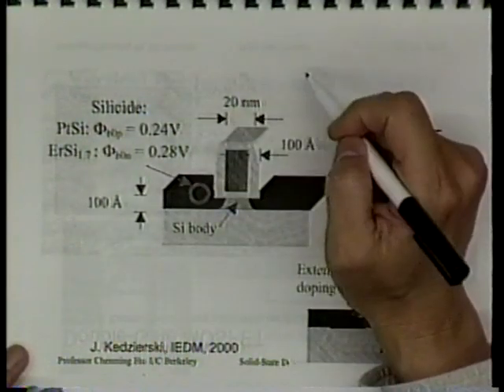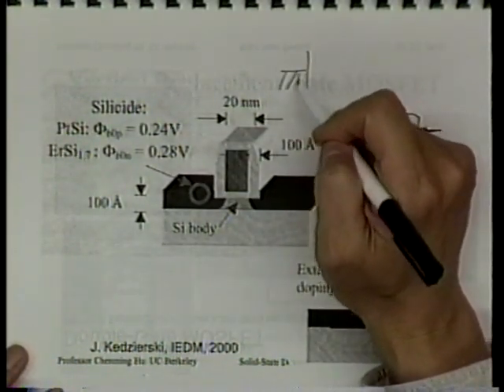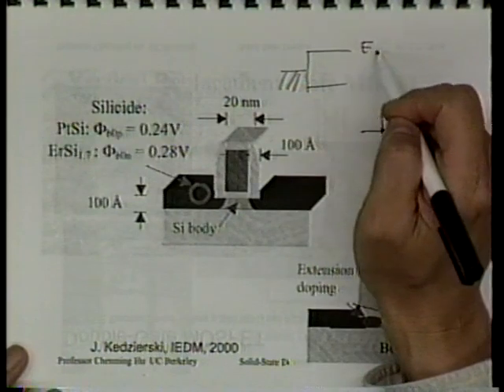Today, we use one kind of silicide to make ohmic contact of both N-channel contact to N plus and contact to P plus material. We use the same type of silicide. So in this case, we better choose a silicide whose work function comes up to the middle of the band gap of silicon, so that for both P plus and N plus contact, for both electrons and holes, we have half of the EG as the barrier. This is what I mean. You want to choose a material whose work function comes to the middle of EC and EV.